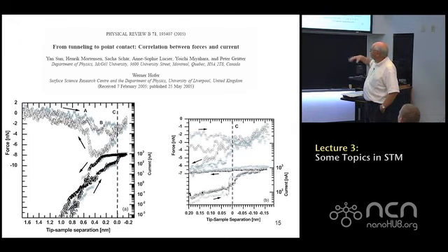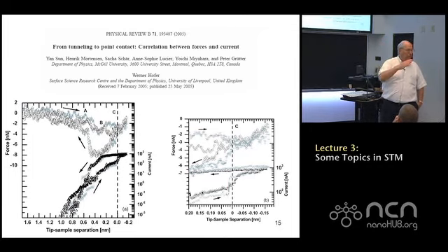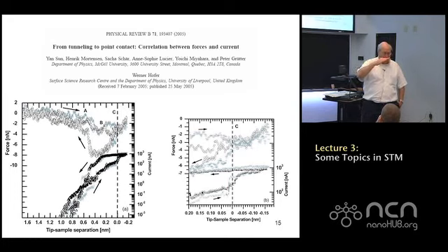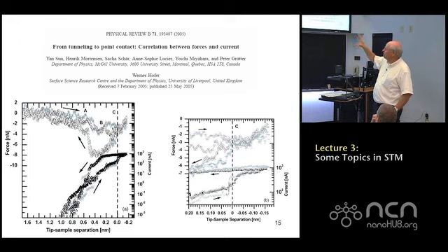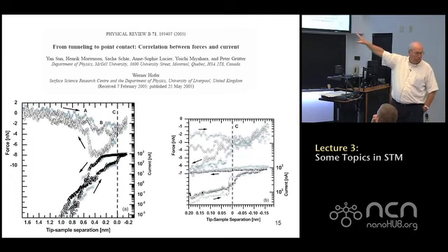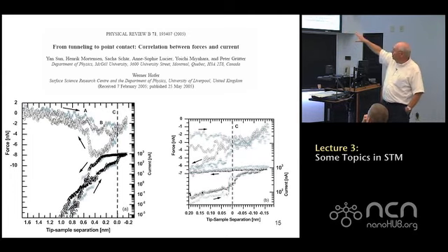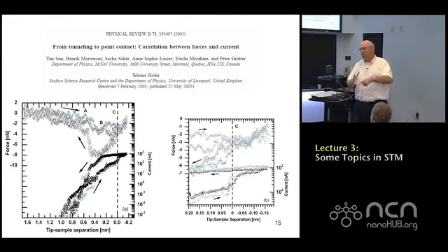And from this data, again, they were able to infer forces because they were measuring the deflection of the cantilever, the angle of the cantilever as it deflected. They monitored that very accurately. The forces they were getting were on the order of 10 nanonewtons or so. In the force distance curve, there's a bunch of data points; you have to look at the original publication to sort it out. But you can see that the force distance curve is hysteretic. You get a different value coming in and going out. And of course, that difference is because the tip is physically stuck to the substrate.